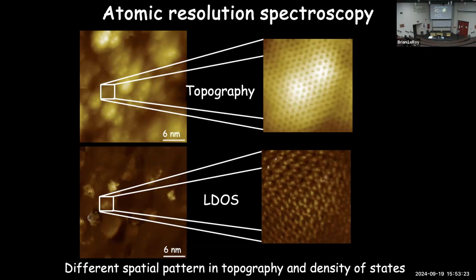But if I go in and do the same thing here, I have some pattern down here in this local density of states as well. And you probably need very keen eyes to notice, though, that they are different from each other. So this topographic, showing us where the atoms are, is varying from here where the density of states, where I can tunnel into the system. Right? So there's not a one-to-one correspondence here. And the difference here is due to some electronic band structure things in the graphene. And so that's going to give us information about the allowed scattering and the different electronic properties. And that's what we're going to use to probe these materials.